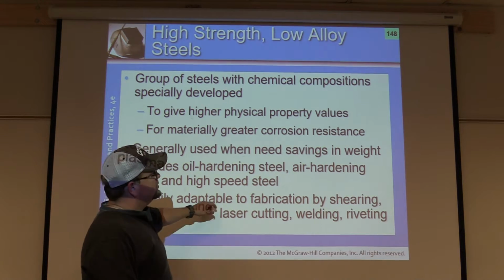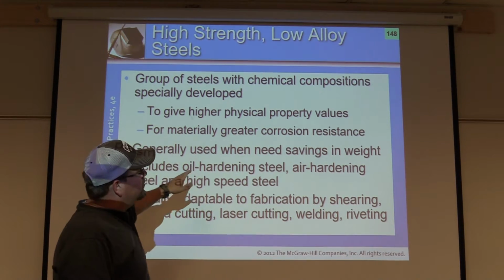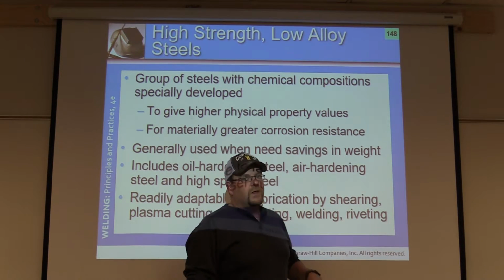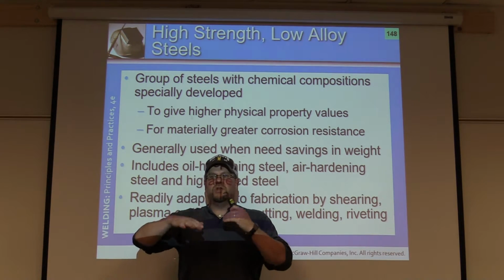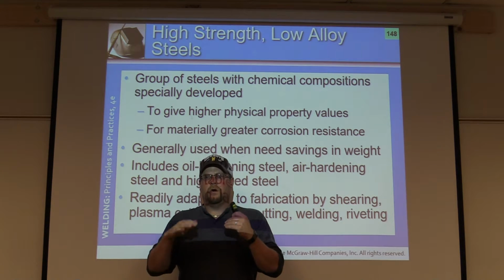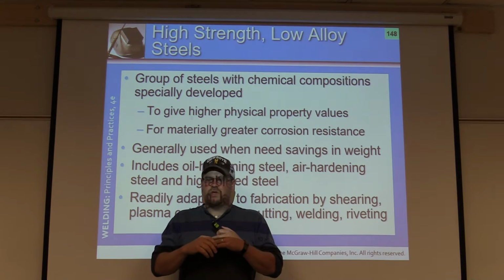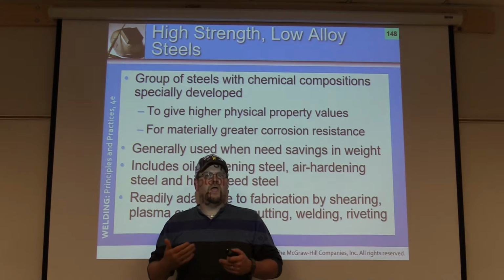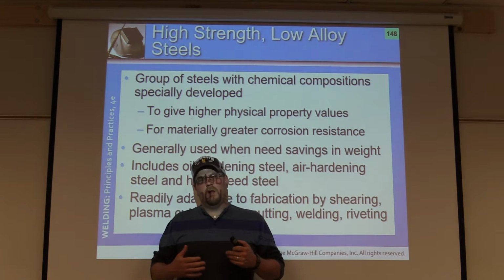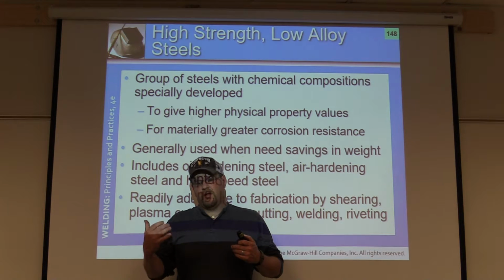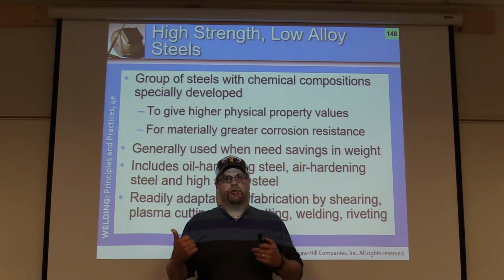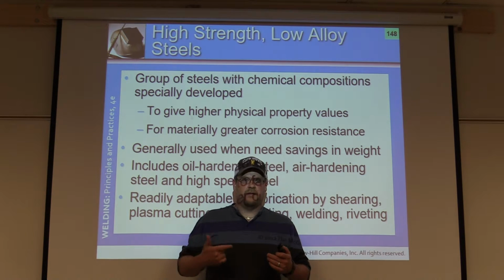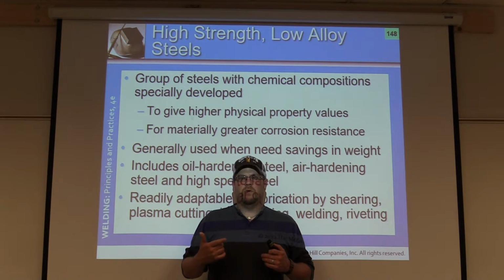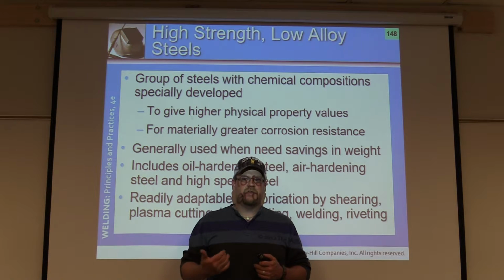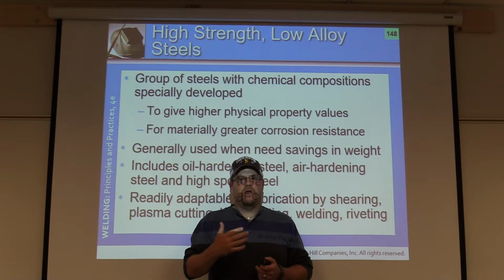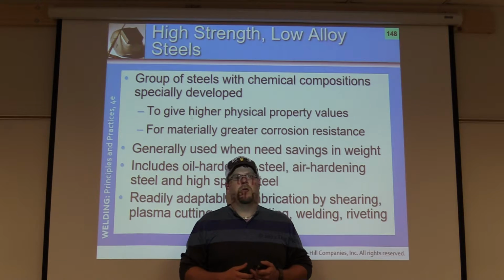A lot of times bushings are made out of high strength, low alloy steels. Now when you're welding these two materials together, say you're welding a bushing inside of a mild carbon casting or mild carbon steel, usually you want to use a stainless filler metal or a high grade. Preheat everything really well, and then you're either going to be using 309 for dissimilar metals or a stainless steel filler metal to weld both of them up, or you would be using a E7018 low hydrogen with a very high tensile strength and a preheat usually of 400 to 500 degrees, okay?